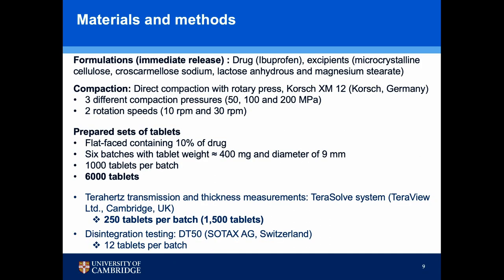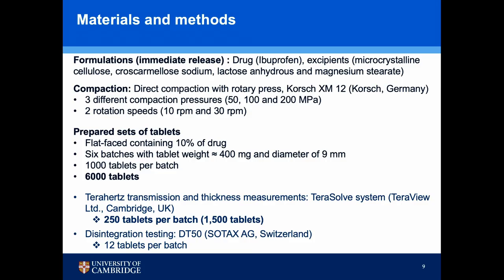To demonstrate how we can use Terahertz sensing to track the properties of tablets based on process parameters, we compacted flat-faced tablets — about 1,000 per batch — using the Korsch XM 12 machine. We used 50, 100, and 200 MPa compaction pressures, and 10 and 30 RPM speeds, giving us six batches in total. Under each batch, we made 1,000 tablets, so in all, 6,000 tablets were compacted.